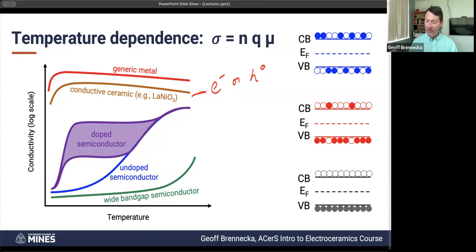So if we're talking about an ion conductor, then that is going to increase a lot with temperature because, even if the number of species doesn't change a lot, the hopping mobility will change. And I guess it won't bend up quite as much as that. It'll be much more linear. It'll be something along those lines. So this would be for ionic hopping.